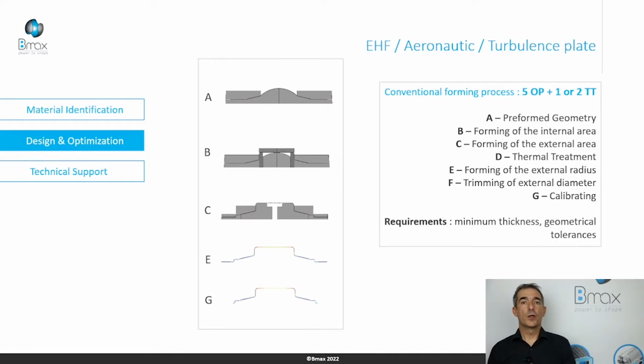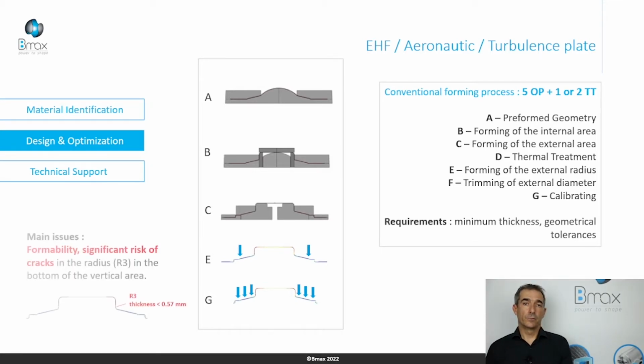At this point, the customer proceeds to a thermal treatment to relax all the stress in the blank before performing a calibration of the external radius. After, there is a trimming of the blank before a global calibration of the conical shape. The requirements are the minimum thickness and a set of geometrical tolerances. With this process, the main issue is a significant risk of crack in the radius R3, at the junction between the vertical wall and the conical shape.